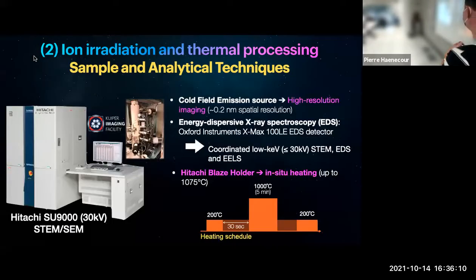Okay. And then, similarly to the first experiment I showed you, we did all the heating here at the U of A in the Kuiper facility using the 30 kV SU9000 STEM SEM. In this case, we did flash heating, a longer flash heating going to 1,000 degrees for a period of about 5 minutes, and then imaging again at 200 degrees, combining both EDS and imaging.